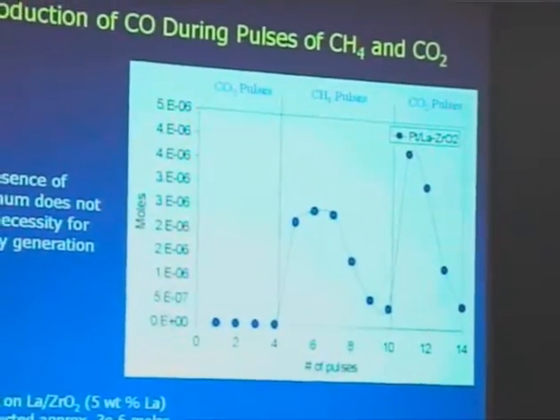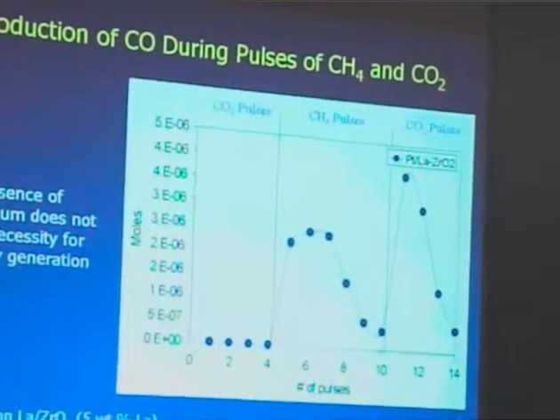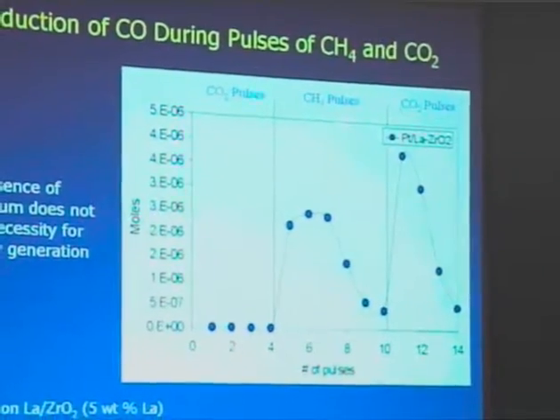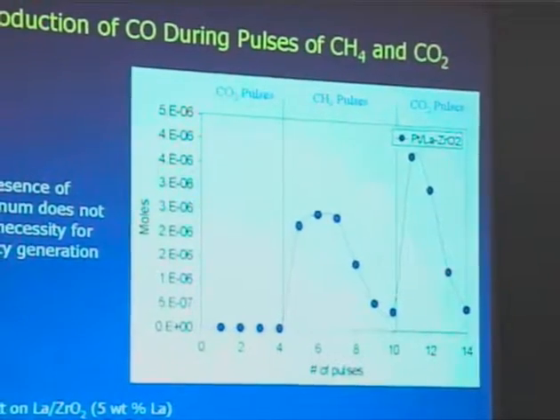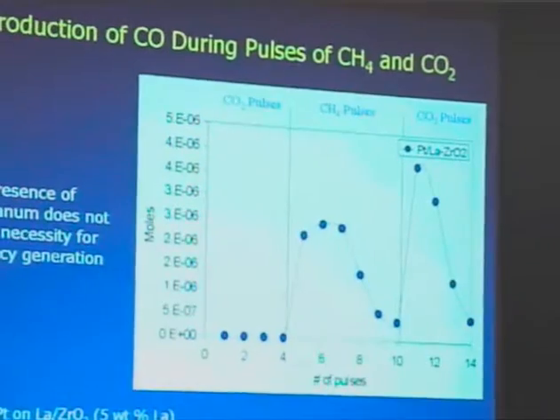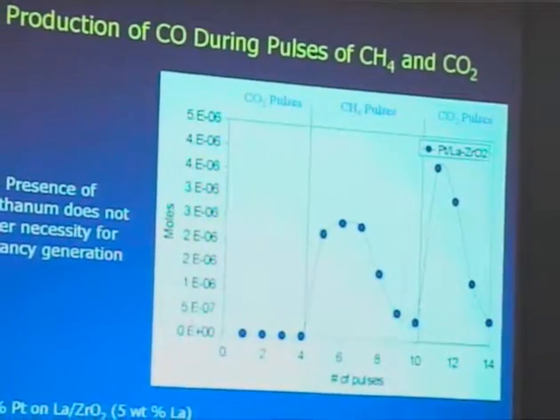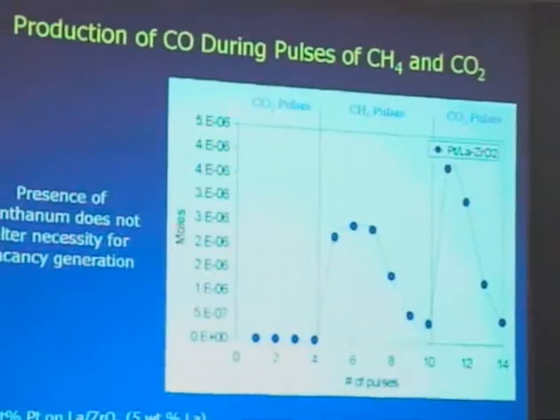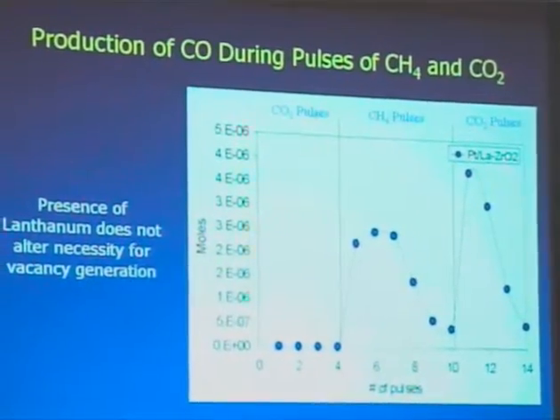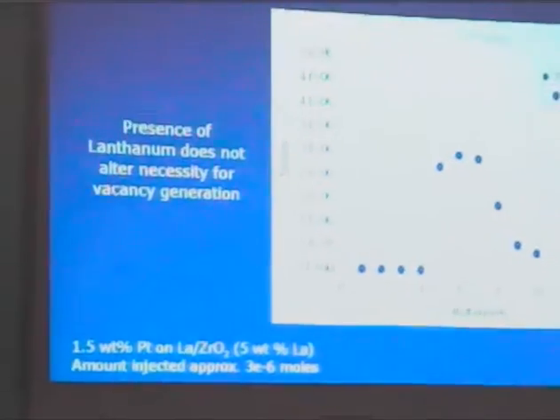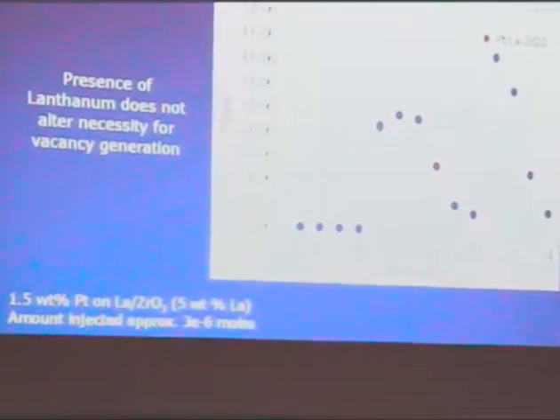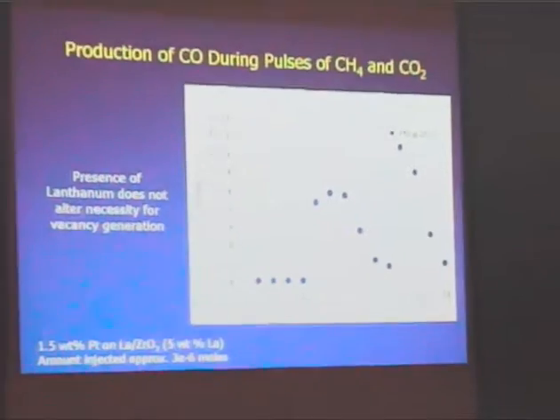What you can see is during the first case where we have reduced it at low temperatures and heated up to 800, we don't see any CO2 or CO formation during those first set of CO2 pulses. So we are not seeing CO2 dissociation. When we have the methane pulses following, we now see the production of CO, again showing some reduction and possibly some dissociation of carbonates that may have been formed on the surface. Now when we do subsequent pulses of CO2, we see the formation of CO, indicating that the oxygen vacancies are necessary for that dissociation of CO2 to occur.